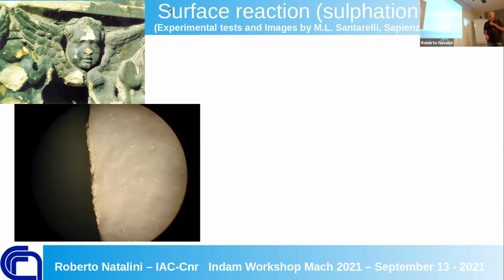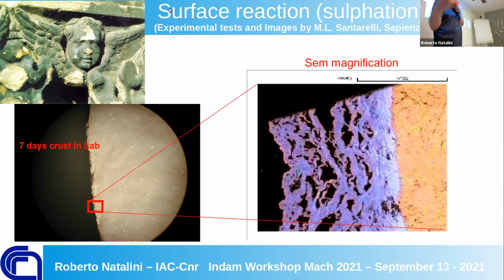Here there is an experiment made many years ago by Roberto Natalini in Rome. Here you have a layer produced in the lab of Sapienza after an exposition of 7 days to full concentration of SO2, 100% humidity. And you have this layer, which is, you see, there is a thin front between marble and gypsum. And this part is completely inhomogeneous, and this grows on the boundary. And so what we want to understand is how to study this kind of crust.